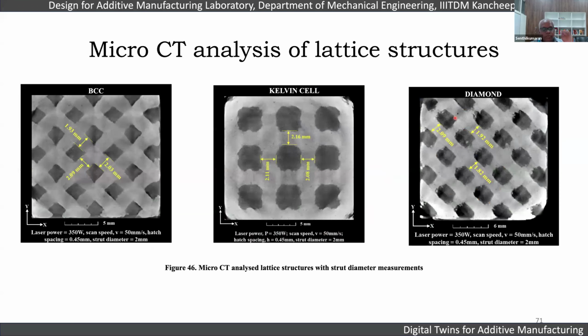This is one example of a micro CT analysis we have done for BCC structure, Kelvin structure, and diamond structures. You can see the distortions at different process parameters. One of the very important learning outcomes is that when we use struts of very high diameter, we get high distortions. When we use struts of lower diameter, we get lower distortion. But the distortions are always on the positive side. Of the 3 dimensions, only one is below the nominal dimension, whereas mostly it is above the nominal dimension.